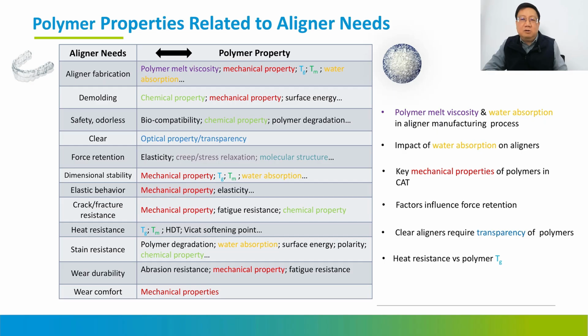Stain resistance is also one of the most important performance properties, because it is related to the surface structure. Some aligners don't use a protective film, and if the patient wears the aligner without a protection film, there are very clear laminate structures from the 3D printing of the dental model. Which means the aligner also shows this kind of pattern on the surface. So you can see the liner is not so transparent, and then you have a lot of chance for material stain on it, a lot of tea or coffee stain, so its stain resistance is very poor.